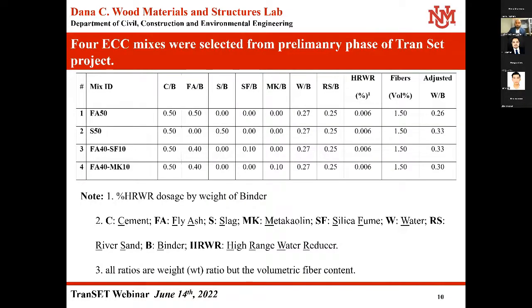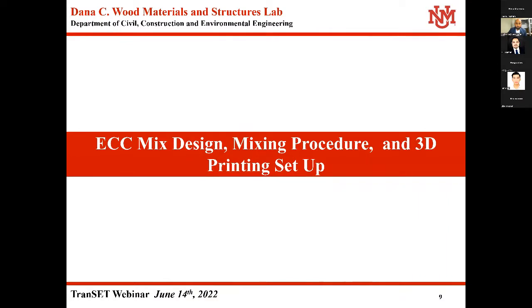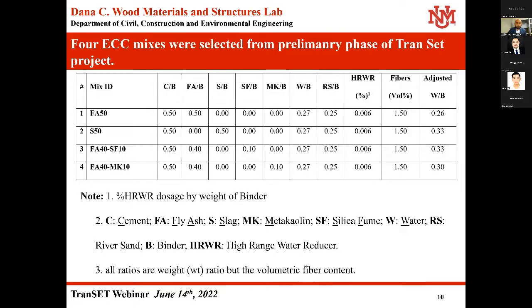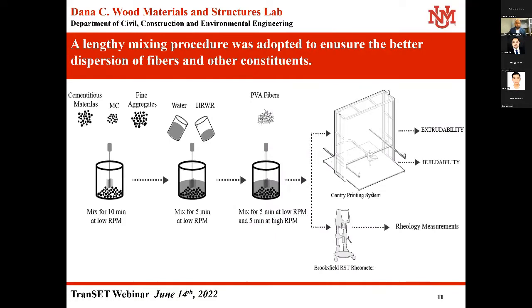In the first, preliminary stage, we worked on the mix design of ECC. The mixing procedure was another challenge, to get better dispersion of the fiber in the mix. From the preliminary stage, we adopted 4 mixes containing fly ash, slag, silica fume, and metakaolin. The fiber we used was PVA fiber, 1.5% of the total volume. This is the mixing sequence, quite long, consisting of 3 stages. The first stage was dry mixing for 10 minutes, then mixing after adding water and superplasticizer, and 10 minutes in the last stage, after adding the fiber, to get better dispersion of the PVA fiber.